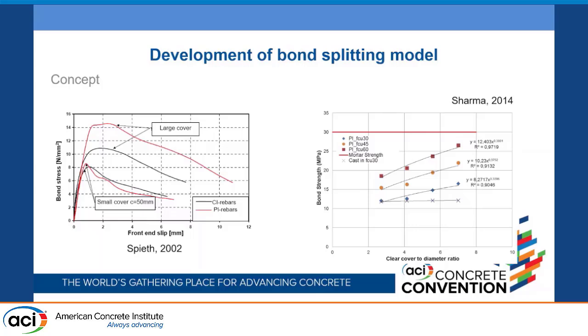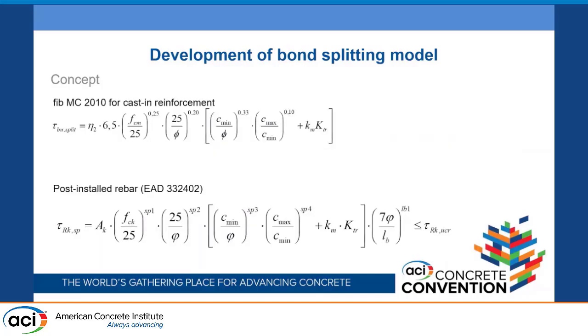In 2014, we performed some numerical studies first, and we showed that in the case of post-installed rebars, given that your bond strength is quite high, with increasing cover-to-diameter ratio and increasing concrete strength, you can achieve much higher bond splitting strengths. For cast-in bars it saturates at, let's say, 3 times the diameter as the concrete cover, but for post-installed we could increase the strength quite high.